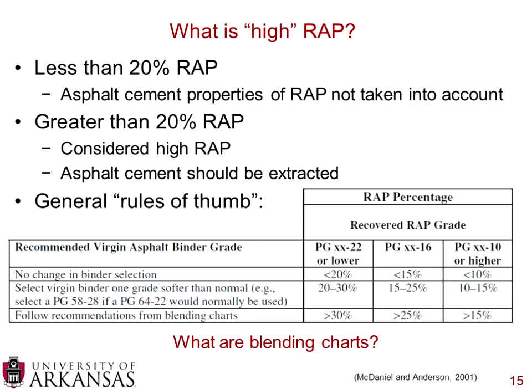In general, the informal definition of high RAP is anything more than 20%. And when you look at that breakover point, there's a couple different things that you can do. So if you're using less than 20% RAP, the asphalt cement properties of the RAP is not taken into account. That means that that blending of the asphalt cement from the RAP with the virgin asphalt cement does not significantly affect the properties. But if you use greater than 20% RAP, this is considered the high RAP amount, and the asphalt cement should be extracted. And you can extract the asphalt cement from the RAP. You can even blend it with the virgin asphalt cement to determine what your final asphalt cement is anticipated to behave like.